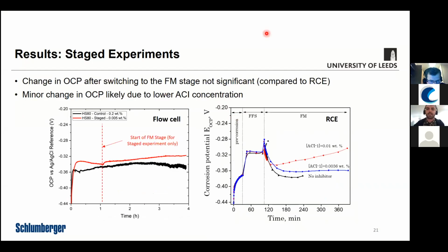So, as I said, one of the challenges that was noticed during the rotating cylinder electrode experiments is you get this OCP spike when the coupons were transferred and exposed to oxygen, which we don't see in the flow cell experiments. This is the flow cell experiments on the left.